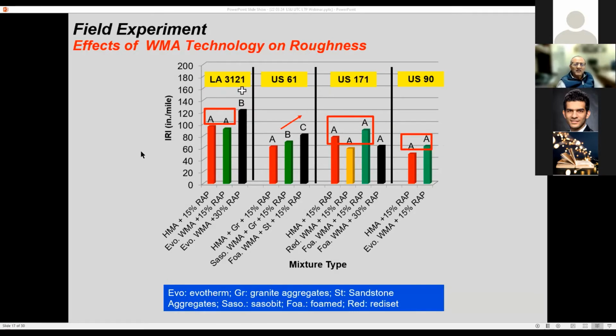The next thing that is in here is the roughness of the pavement as documented by IRI. And in these particular variations of routes, one can see that, again, in general, the WMA mixtures had at least statistically similar roughness to the conventional mixtures. This one right here on the LA 3121, you see that higher RAP content showed slightly rougher, because we did see that it's got a little bit of rutting, so you would expect that to be rougher.